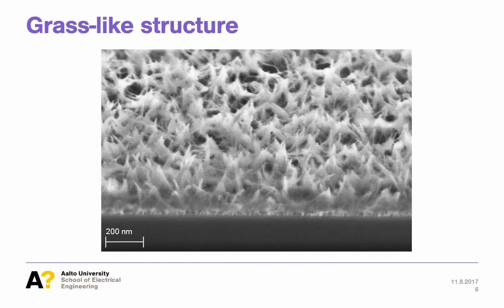This is a scanning electron microscope, or SEM, image of grass-like alumina. The water treatment does not etch the film, but it expands the alumina by dismantling the ALD-grown film into flakes or fibers that are still connected to the substrate, lifting them up. Partial delamination occurs. In such a way, the film becomes porous, with the size of the features below 100 nanometers. As you can see, the film indeed has a grass-like structure.